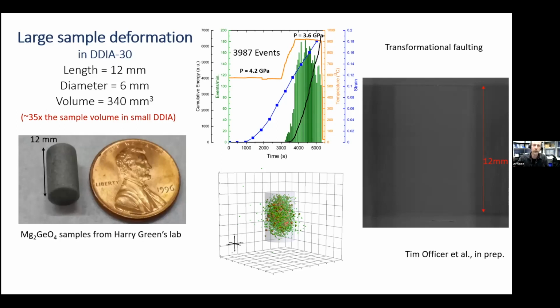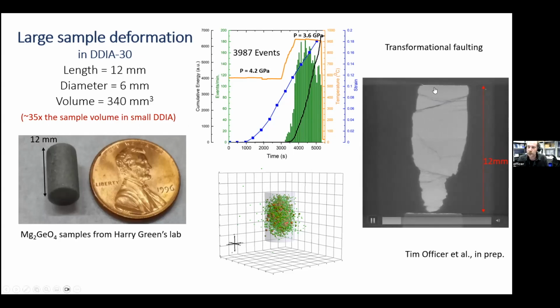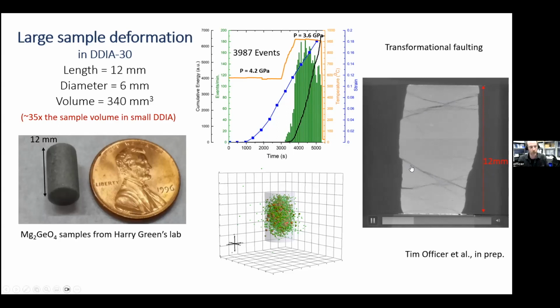Didn't show a diagram, but I suspect for this type of sample, which is 12 millimeters by 6, I actually have one of these, and this one you can sort of see. Yeah, so we get, I would estimate probably a factor of 10 times the amount of acoustic activity. And then this is just a CT scan showing going through. We can also change the aspect ratio. So before, we have stress concentrations near the top, which tend to generate fracture, but now we can move the fractures away to have them happen near the center of the sample.